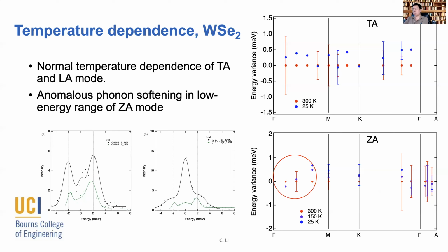And we repeat this in several Brillouin zones. The results are reliable, and we can clearly see that for the ZA mode, which is a flexure mode, by decreasing the temperature, the phonon mode will soften. And on the other hand, if we heat the system up, the phonon mode will harden.